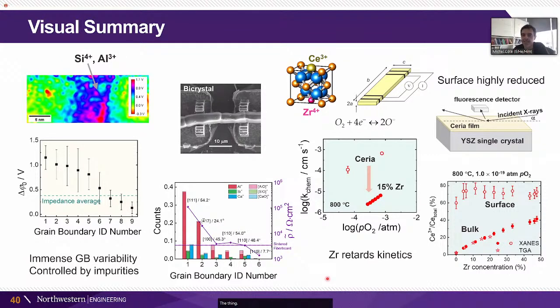Hey, thanks very much, Sossina. Really nice talk. Just to follow up on this discussion about the importance of electronic structure, I think it's really important to emphasize for the folks listening here too that this ability for cerium to change its oxidation state back and forth, depending on the dopant concentration or the local oxygen vacancy concentration, is actually very interesting as well from an electronic structure point of view, purely, not even just thinking about the X-ray spectroscopy.